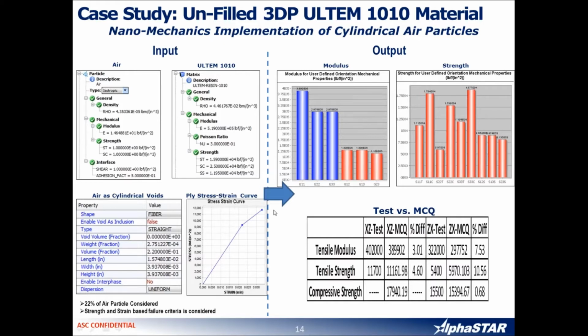There's also applied stress strain curve, which is also part of the input of this software. The output that we get out of this MCQ Chopped software is a modulus in each and every direction, as well as the strength. And these were also test validated for multiple cases, for the tensile modulus, for tensile strength, and compressive strength. And as you can see here, the percent difference is very low, about 3 to 4% in the XZ direction, and the ZX direction is less than almost 10%. So that shows that the material calibration that we have done in our input for the MCQ Chopped is valuable and can be test validated.